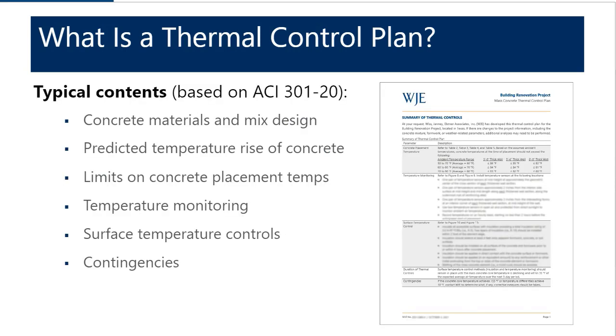So typical contents will include things like the concrete materials and mix design, the predicted temperature rise of the concrete, which will be based on the concrete materials and mix designs, the element dimensions, the boundary conditions, and so on, all of those factors that I talked about before that contribute to the definition of mass concrete. It will include limits on concrete placement temperatures, which are based on those predictions of predicted temperature rise. It'll include instructions for monitoring the temperatures in the placement to make sure that those limits aren't exceeded. It'll include surface temperature controls, things like applying insulation to make sure that the differentials aren't exceeded, in addition to how long those controls need to remain in place.